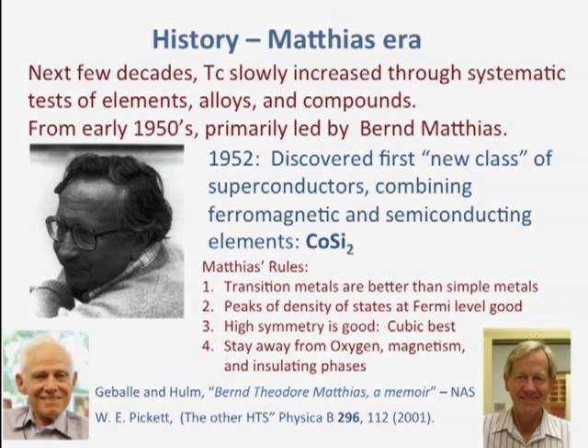These next two just don't work at all for the high TC. High symmetry is good, cubic is best. In fact, the high TC materials, the more layered, the higher TC, and stay away from oxygen, magnetism, and insulating phases. All of the high temperature superconductors are, in some cases, quantum critically next to those phases. So it's not that Matthias was wrong, it's just that he was correct for the s-wave metallic superconductors. This was before the high TC were around. In fact, towards the end of his life, he wanted to start looking at oxides, and everyone thought he was crazy, but you know, he wasn't. Brilliant guy.